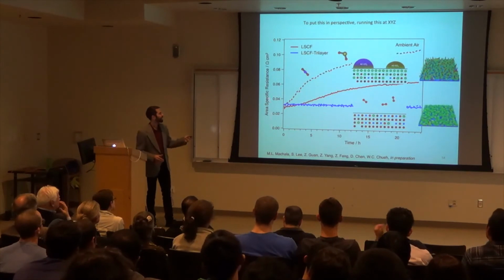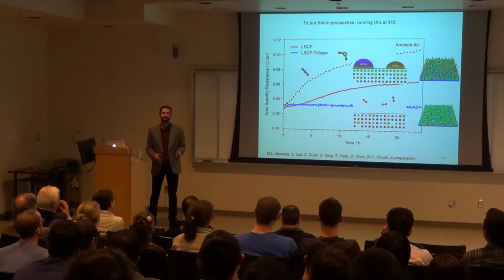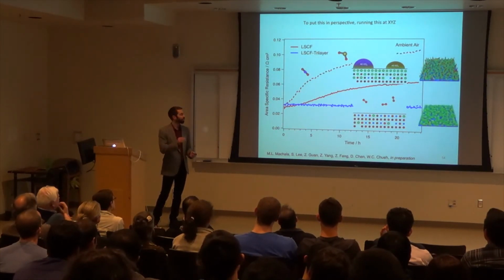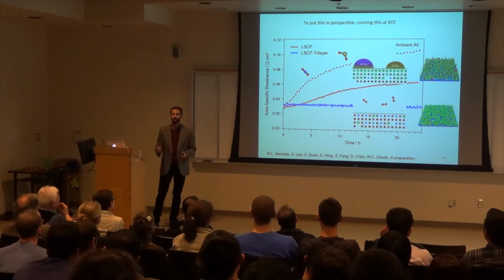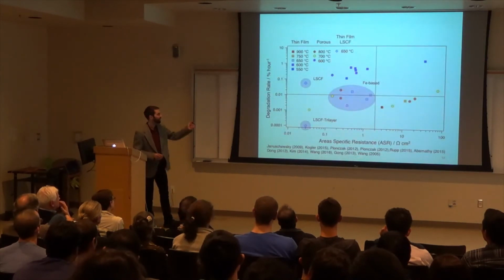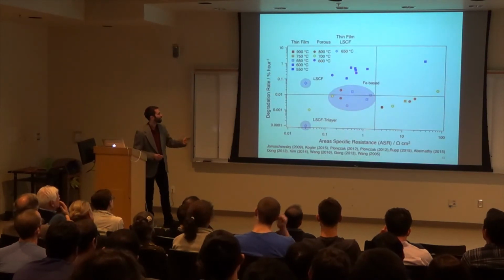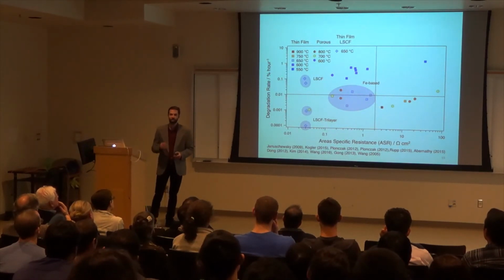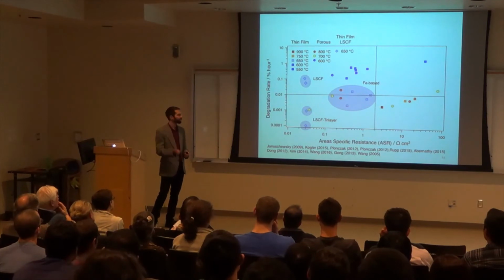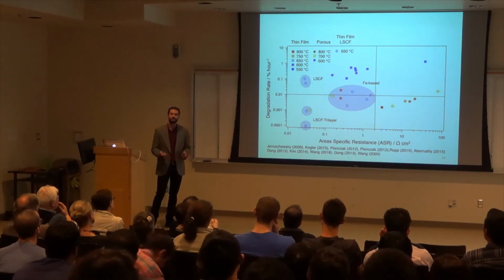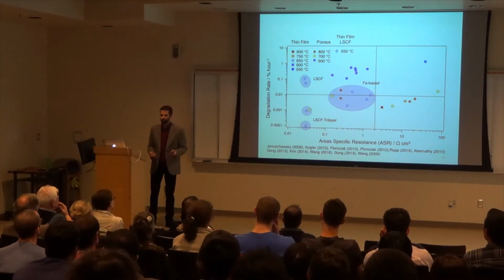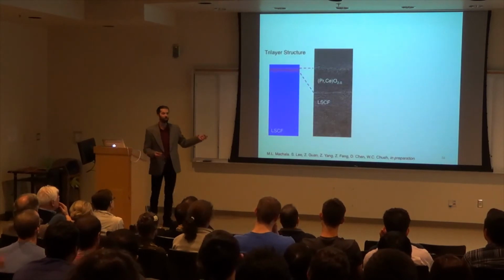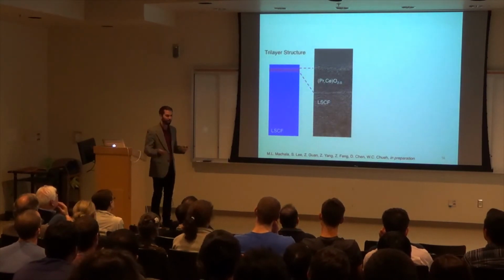Now, to put this area-specific resistance in context, 0.03 ohms, when you apply 100 millivolt overpotential, is about 3 amps per centimeter squared current, which is pretty good. So when we focus on the figure of merit, we see that we're among some of the best catalysts in the world, both in terms of catalytic activity and stability. And we're only using a thin film system. This is not porous yet. So that begs the question, what can we do to kind of scale up into the porous system?